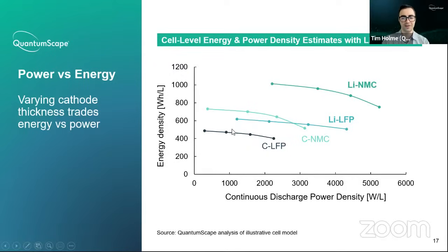This curve in the lower left is what you'll see if you mix a graphite or host-type anode with an LFP. And as we've discussed, it has lower energy density relative to when you have carbon combined with NMC, which would sweep out this curve up here. The varying points on the curve are because in essentially any battery, you can trade off energy for power by varying the thickness of the electrodes, for example. So here we're just picking a few points on that space to look at the frontier of energy versus power.